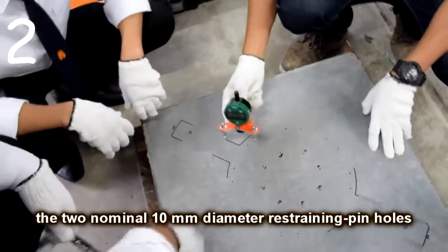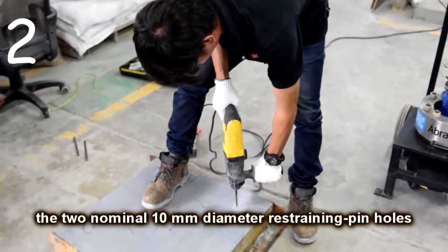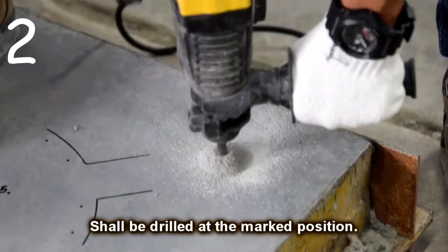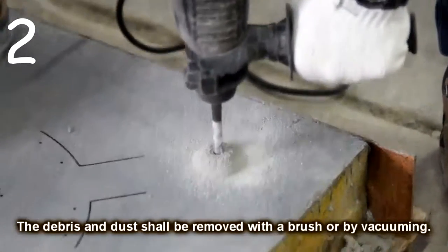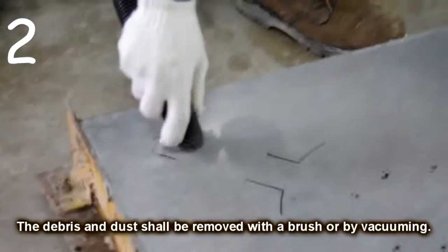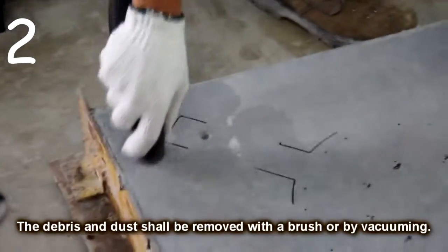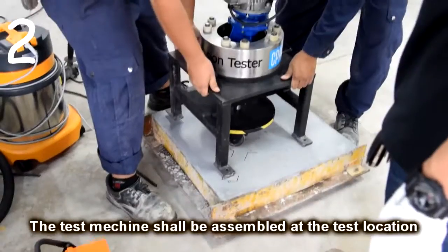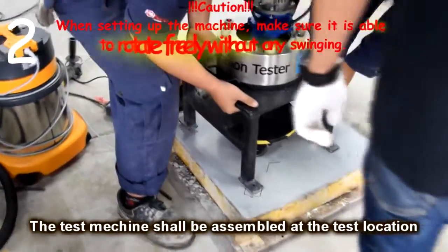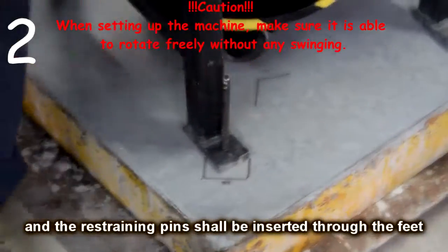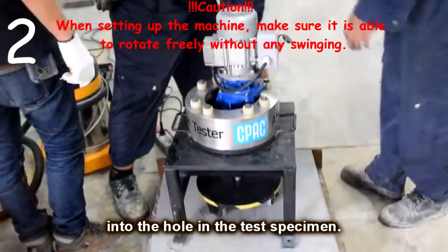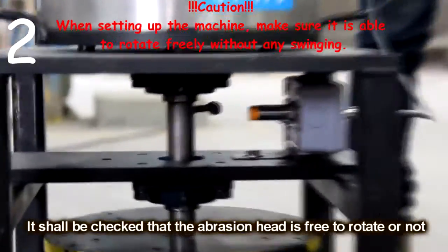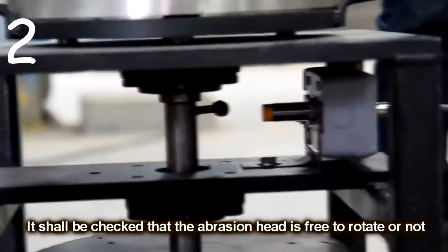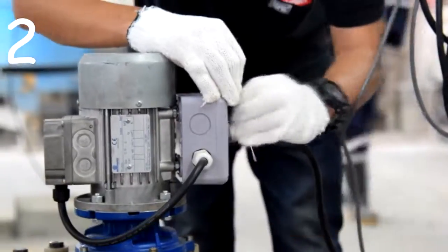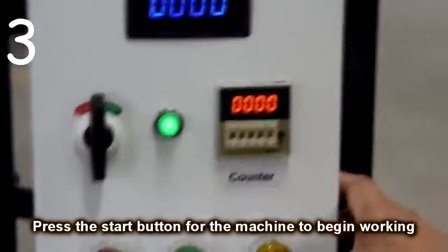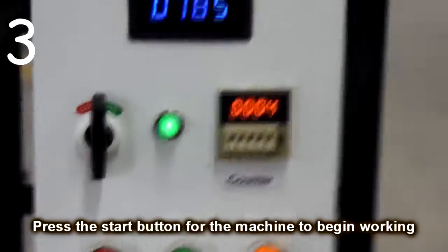The 2 nominal 10 mm diameter restraining pin holes shall be drilled at the marked position. The debris and the dust shall be removed with the brush or by vacuum. The test machine shall be assembled at the test location, and the restraining pin shall be inserted through the feet into the hole in the test specimen. It shall be checked that the abrasion head is free to rotate or not. Press the start button for the machine to begin working.